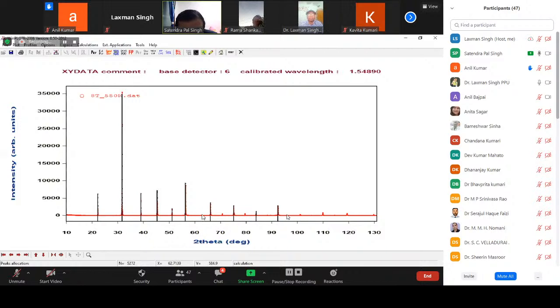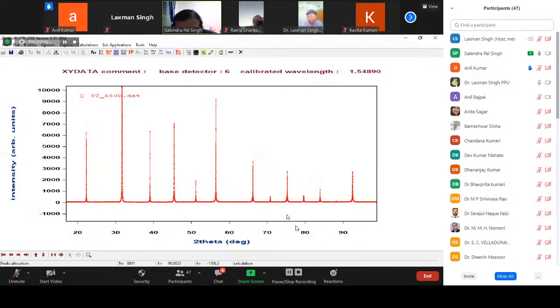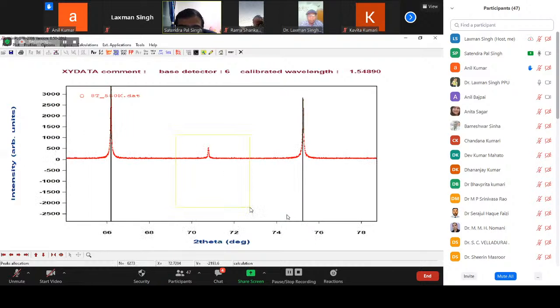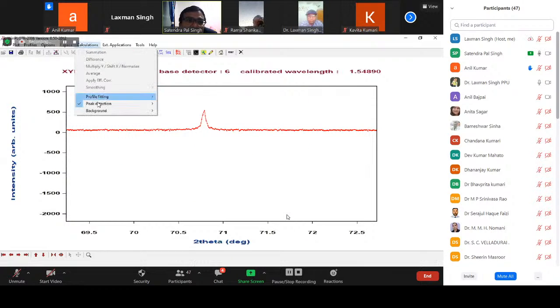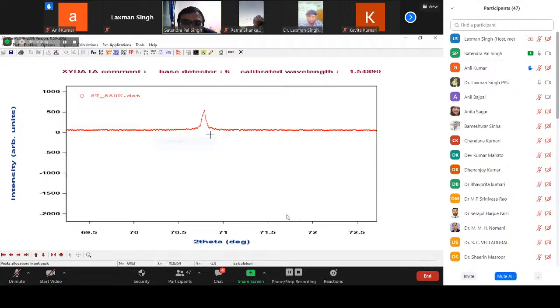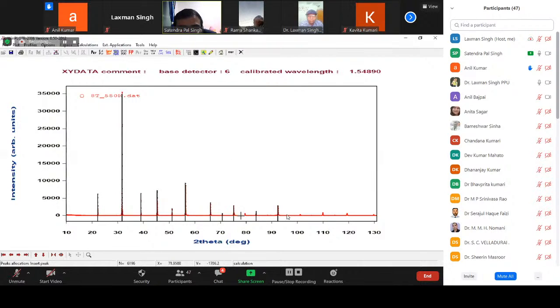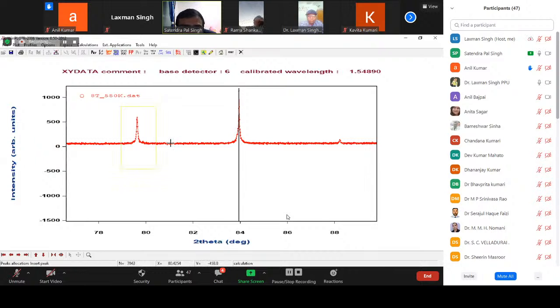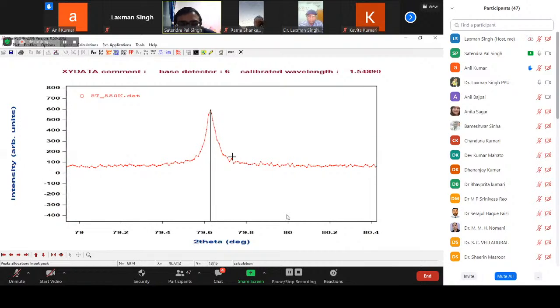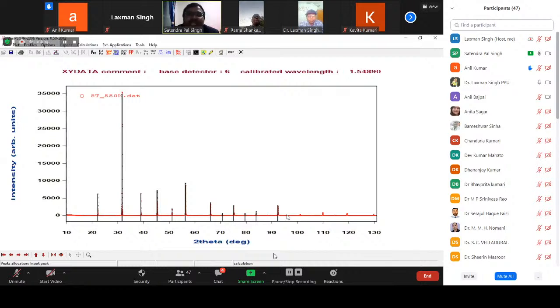Now, see whether all the peaks are marked or not. There are certain peaks, see, this peak is not marked, so we have to mark this peak. This peak is also not marked. We can mark it. The most important thing in indexing is that we have to consider more peaks in the lower 2 theta range. But this pattern has very few peaks in the 2 theta range, so we are going to extend the peak positions into the slightly higher 2 theta range also.